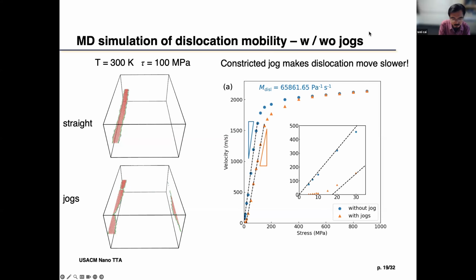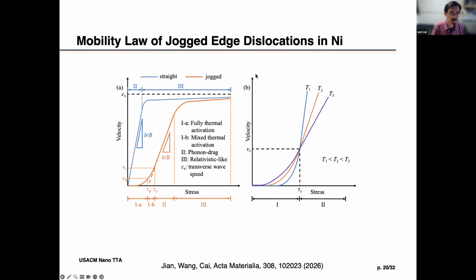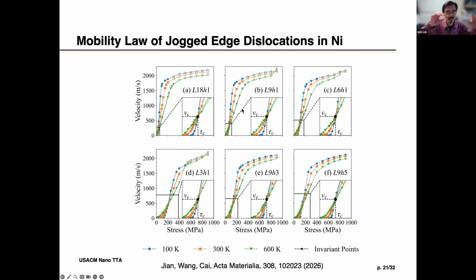Now, I don't think people want to include jogs explicitly, like by modeling a little segment in the DD. That's just not possible. So in fact, in the DD, I would envision a discrete mobility that depends on how many jogs it has on every segment, okay? But then how do you get that mobility? Well, we try to do it from MD simulation. Here there are different configurations, all dislocations with different numbers of jogs on them. But you can imagine it's very tedious. I'm not sure whether this can be done all by high throughput, and then we just get something out of there, or maybe after a sufficient number of simulations, you try to develop some kind of rule, right? Because more jogs mean more resistance, right?